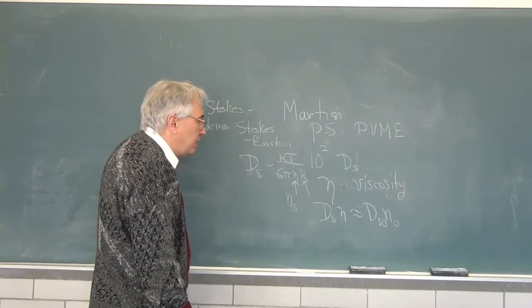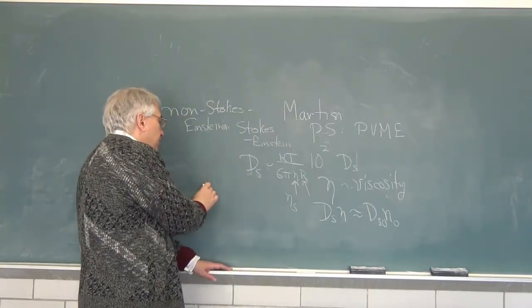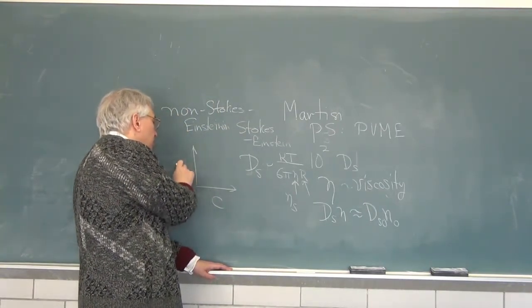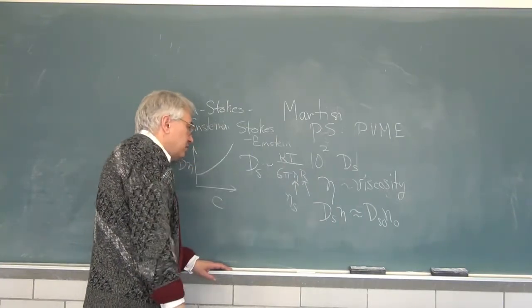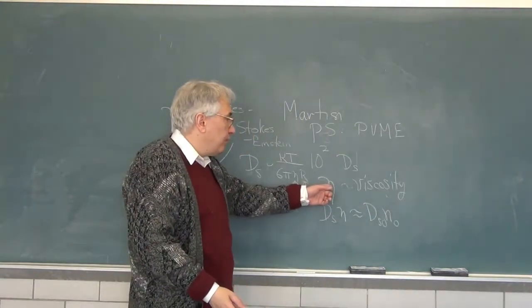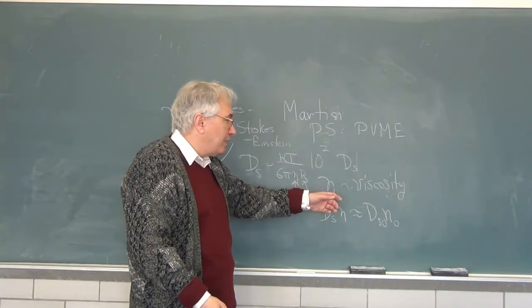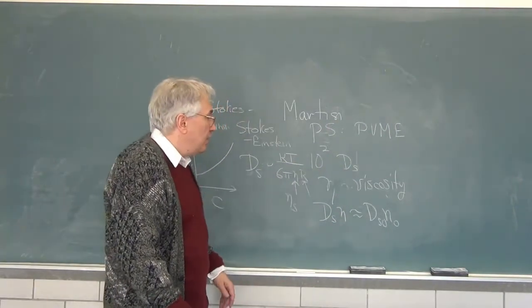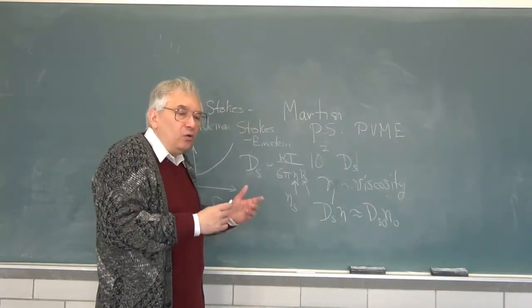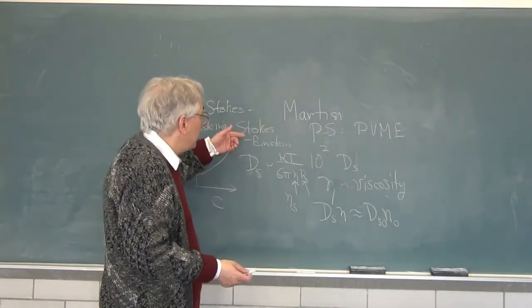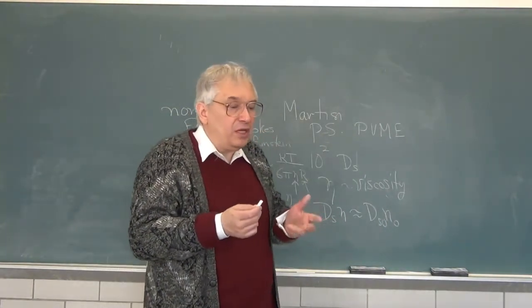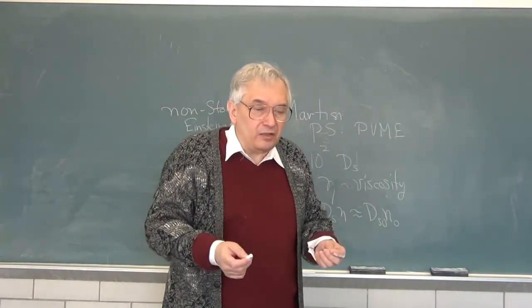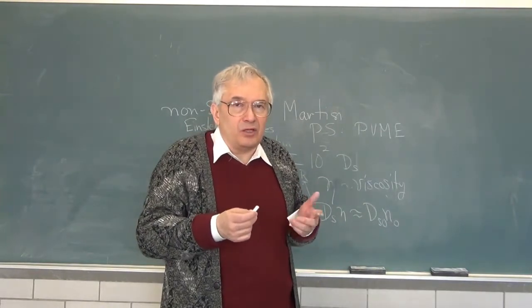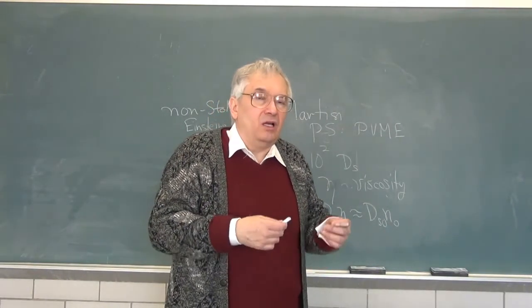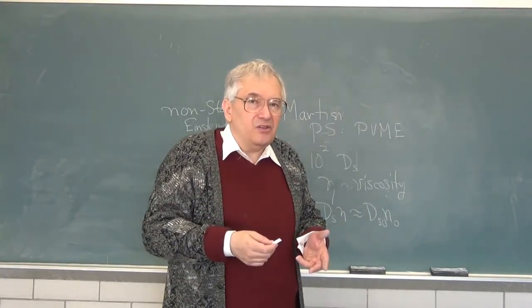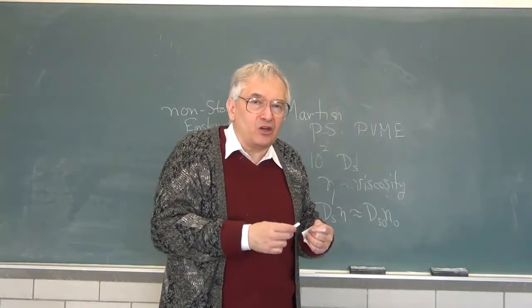in almost all cases. The non-Stokes-Einsteinian behavior is that as you increase the concentration of the system, the product D eta also increases. That is, the matrix polymer is more effective, sometimes orders of magnitude more effective, at increasing the viscosity of the solution than it is at retarding the diffusion of polymer or hard sphere probes. That's non-Stokes-Einsteinian diffusion, but it's fairly unambiguously observed by Martin for polymer coils. Unfortunately, there is not nearly as much data as one would like where people compare chain diffusion and viscosity, so I can't go into a great deal of discussion of this because the measurements aren't quite there.